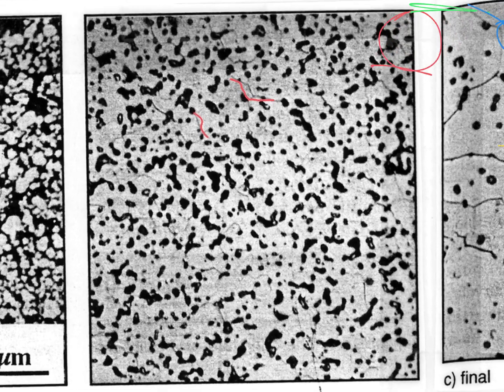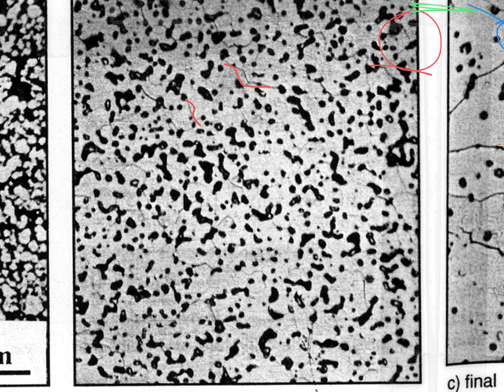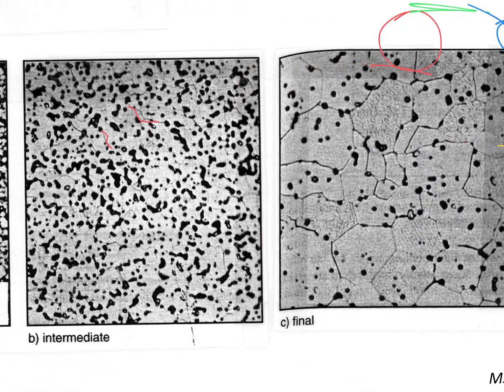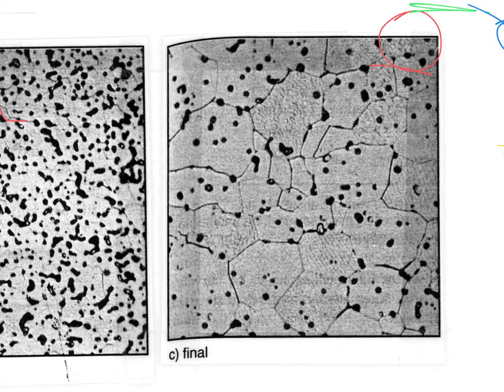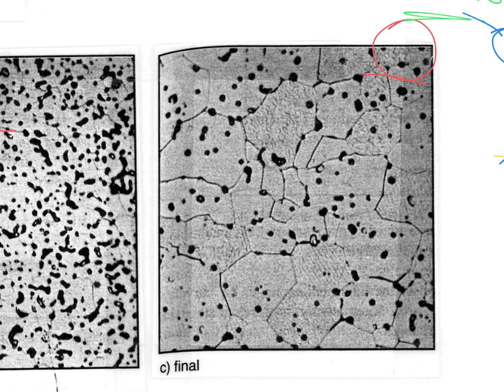And where you want those pores to be, of course, is on the grain boundaries, and it's kind of hard to see anything here. You occasionally make it to a grain boundary, but lots of dark pores. And then as we go toward what they call the final stage in this context, that's where you see success and disaster. So you see some pores sitting on the grain boundaries, doing what they should do, diffusing the contents toward the surface, but then you have others that have gotten put inside the grains. All right, so if you let this sit at temperature, what you'll see is those pores in the grain boundaries will disappear, whereas the pores in the middle of the grains will still be there. You'll still be able to see them. All right, and that's a measure of how much more efficient diffusion along the grain boundaries is versus diffusion within a grain. So everyone follow that?